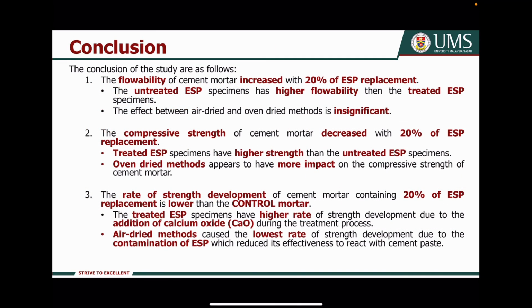As for the conclusion, for flowability, the untreated ESP specimen has higher flowability than the treated ESP specimen. Meanwhile, the effect between the air-dried and oven-dried method is insignificant. For the compressive strength, the treated ESP specimen has higher strength than the untreated ESP specimen. Meanwhile, the oven-dried method appears to have more impact on the compressive strength. For the rate of strength development, the treated ESP specimen has a higher rate of strength development due to the addition of calcium oxide. Meanwhile, the air-dried method causes the lowest rate of strength development due to the contamination of ESP.